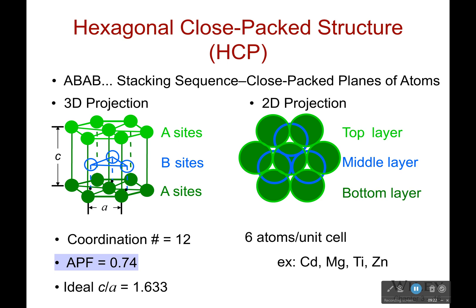The next thing we're going to hit on is the hexagonal close-packed structure. This is terrifying. I just want to go ahead and mention it right now. This is terrifying. It has the same coordination number. Same exact coordination number, which is 12. And the APF is 0.74. But it has an A, B, A stacking sequence. You can see we have one, two, three, four, five, six. That's why it's hexagonal. And it's seventh one in the middle. And we have the exact same thing at the bottom. And then we have just a triangular set in the middle. We will not do many problems with this. There will be a few though, working with the hexagonal close-packed structure. But I won't do this to you too much.